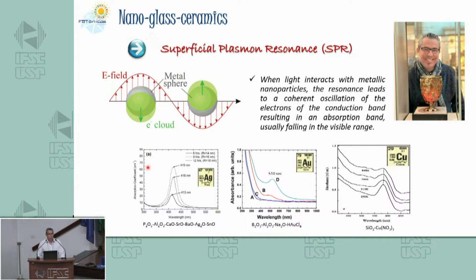There is another very important property here, the refractive index, because for example for silver, this absorption here in silica at 420 nanometers is because silica has a refractive index around 1.5. If you take a glass with a refractive index more or less close to 2, this absorption will shift to the visible, to the green. So they will absorb the green, and then the glass will appear red, usually. So if transparency in the visible is important, we need to play with the refractive index too. Otherwise, we cannot use these properties of these particles, okay?